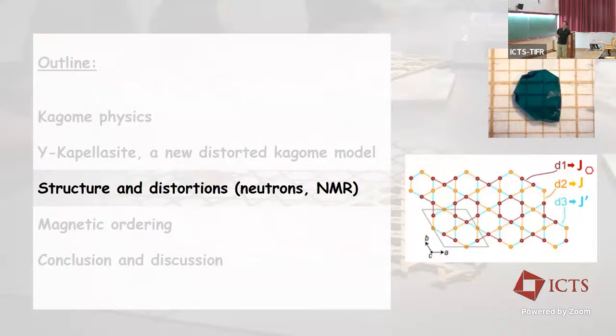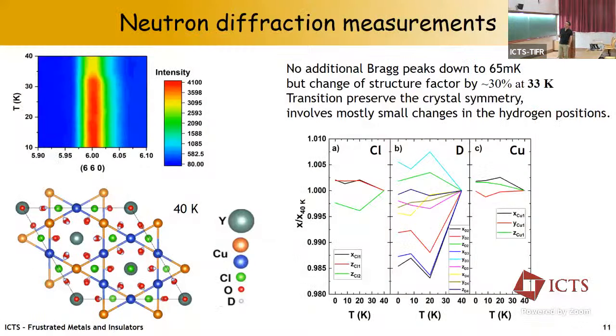Okay, so let me go into a bit more detail first. Before going to magnetic order, let me discuss the structure and distortion issues associated with the 33 Kelvin peaks. So this is neutron diffraction, and in neutron diffraction, we did study from high temperature down to 65 milli-K, and on the whole temperature range, there is no additional Bragg peak, so no change of symmetry, and no signature either of magnetic order.